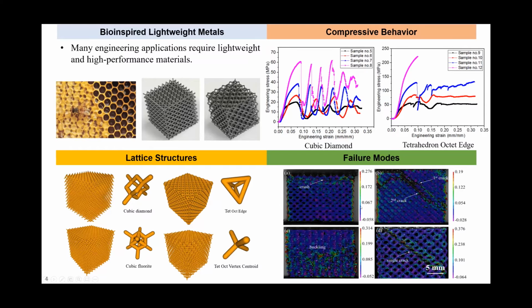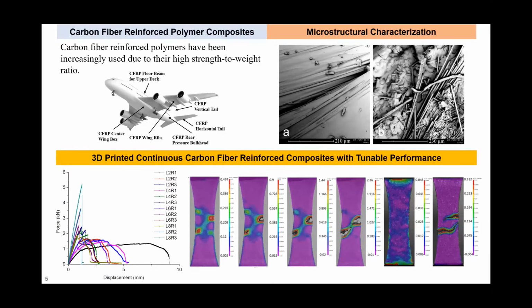So you can see these failure modes include crush, cracks, and buckling. And these are the 4 images we captured using the digital image correlation technique. So using this DIC technique, we can observe how these lattice structures fail during this compressive testing. The second project is about carbon fiber reinforced polymer composite.